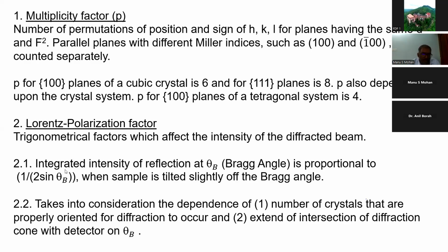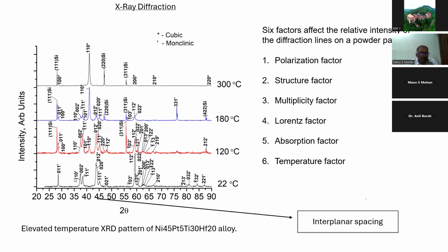If I go back to the previous slide, you can see I've shown two planes, 011 and 110. These two peaks are different in monoclinic because your a, b, c lattice parameters are different. Whereas in cubic, your 011 and 110 will not be different, they will be the same. You can mark it as either 011 or 110, it will be the same because the d-spacing is the same.